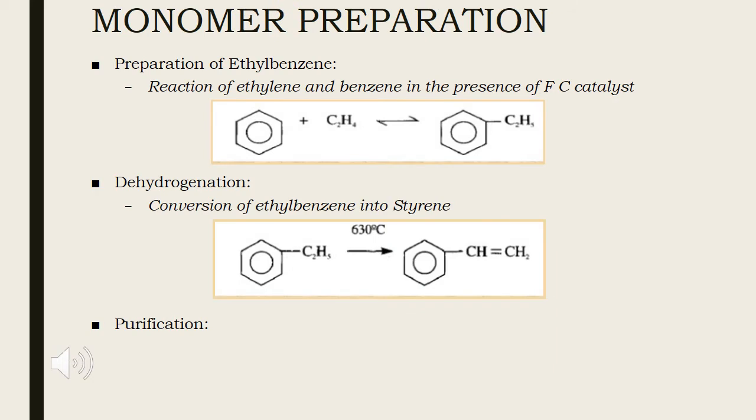For the manufacturing of polystyrene, monomer preparation is crucial. The bulk of commercial styrene is prepared by the Dow process or similar systems, which involves the reaction of benzene and ethylene to give ethyl benzene, its dehydrogenation to produce styrene, and a final finishing stage. It is therefore useful to consider this process in each of the three stages.